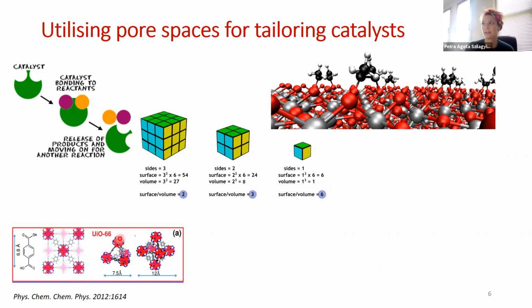So these are hexanuclear zirconia clusters, which are interconnected by terephthalic acid. This is one of the most stable frameworks, and it has two different kinds of pores. One of them is tetrahedral, with a 7.5 angstrom diameter, and the other one is octahedral, and its diameter is 12 angstrom in size.